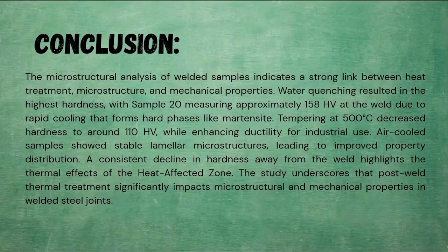Third, all samples consistently showed a decrease in hardness with increasing distance from the weld, which is a direct result of grain growth, phase transformations, and recovery effects in the heat-affected zone. Overall, our findings confirm that the choice of cooling treatment after welding is the primary factor controlling the final mechanical and microstructural properties of welded steel joints.